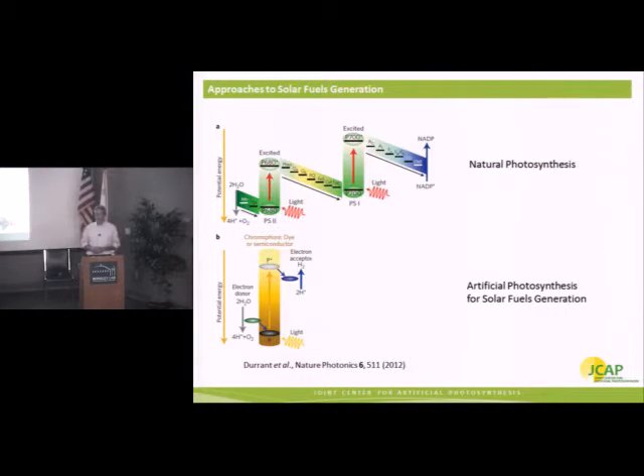The problem associated with this is that you have to first overcome the thermodynamic potential for water splitting, and then also have enough extra potential to work at the overpotentials required for the catalysts to operate. This means that the band gap of the semiconductor you use is typically prohibitively large, because you lose a large fraction of the solar spectrum.